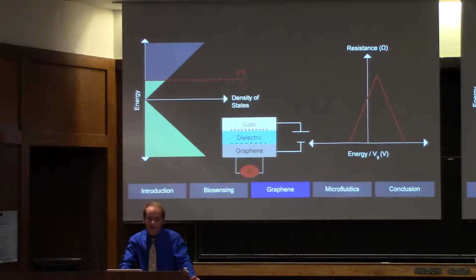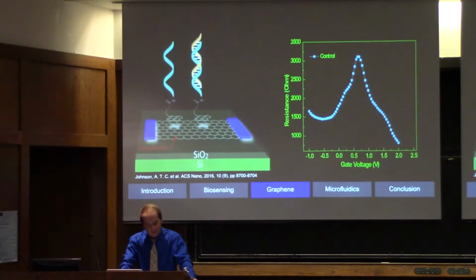You can see all this work here in the sample measurement. We start by taking a control measurement before we've introduced any biomolecules to the graphene. In our experience, this control measurement never actually starts at 0 gate voltage, which is what the theory predicts. But this is probably a result of some minor impurities that have accumulated on the graphene due to the lengthy fabrication process. Nonetheless, the control serves as a reference point for all the future measurements.